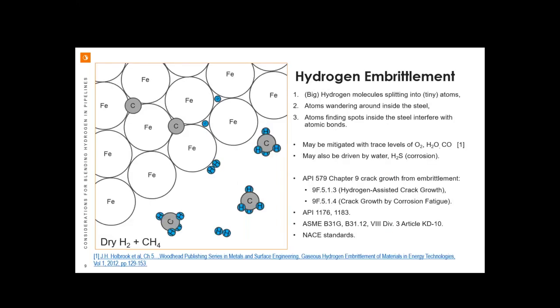Okay, now we've talked about the code and some gaps. I want to talk a little bit about what hydrogen embrittlement is. Within our pipeline, we have diatomic hydrogen molecules, and then other things like methane and some impurities. The diatomic hydrogen has this special ability at ambient temperatures and pipeline pressures to adsorb to the surface of the steel and then actually dissociate into atoms, or if there's a corrosion reaction, maybe even protons. And then they're wandering around in the steel. So this would be a normal occurrence when you have hydrogen gas. The problem is when they all of a sudden start to find spots and interfere with atomic bonds, say between the iron or the carbon or manganese that's in the steel. And that's really embrittlement. It's interfering with those bonds, at least for the purposes of this presentation.